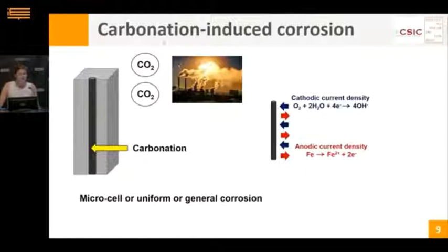The carbonation in the concrete occurs when the concrete is exposed to CO2, which is present in the atmosphere, and the CO2 reacts with the alkaline substances in the pore solution and with the hydrated phases of the cement. This reduces the pH of the system to a value insufficient to maintain the passive state, around pH 8 or 9. The CO2 front penetrates through the pore structure of the concrete, but this process takes many decades, and if the carbonation depth reaches the steel surface, the passive film is not stable anymore.